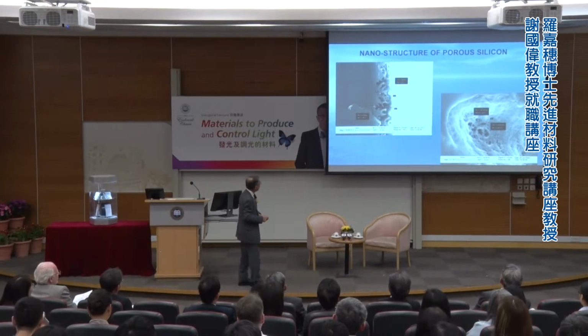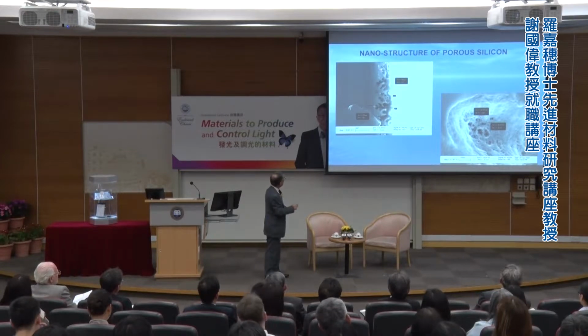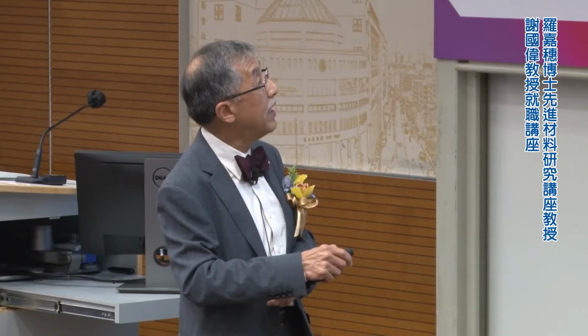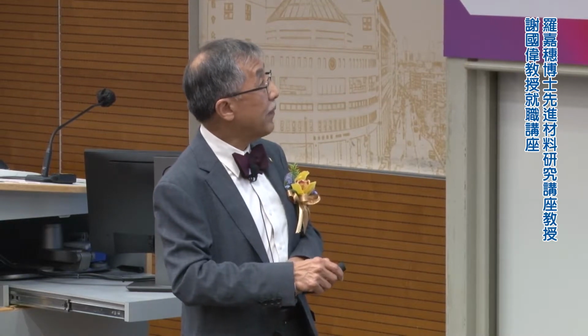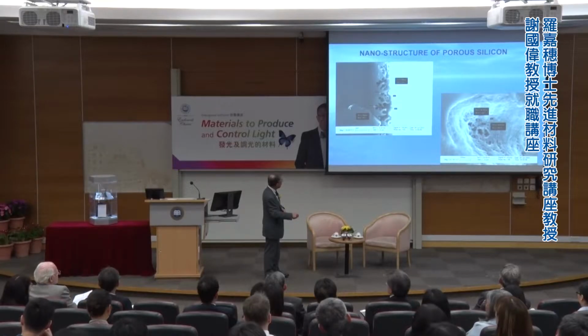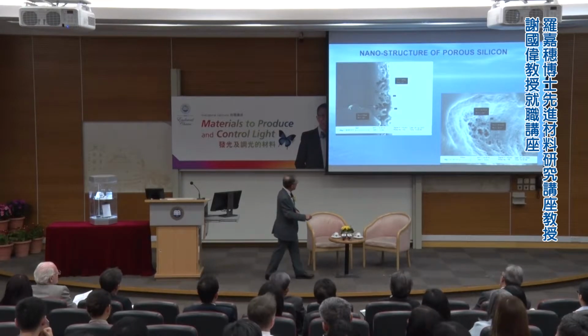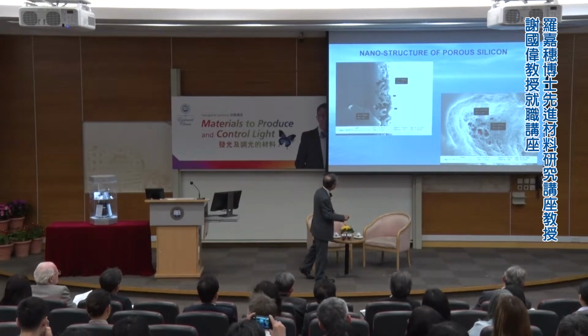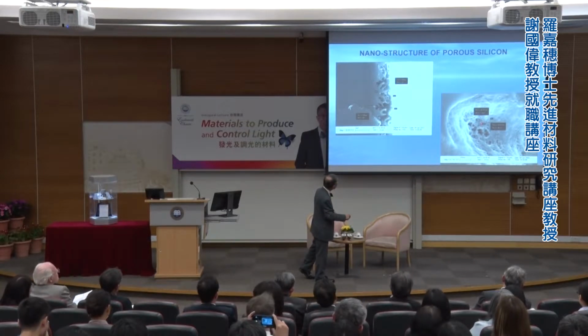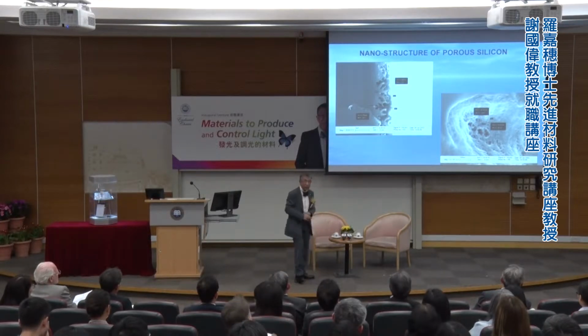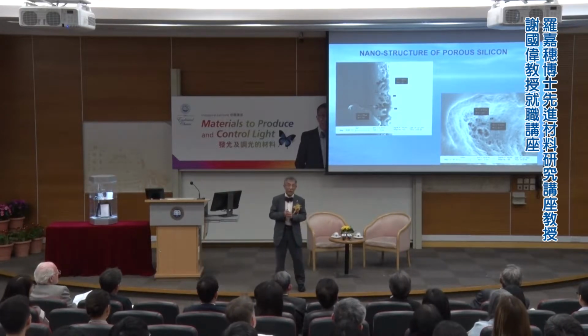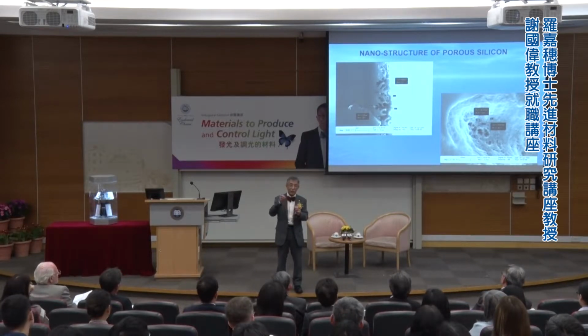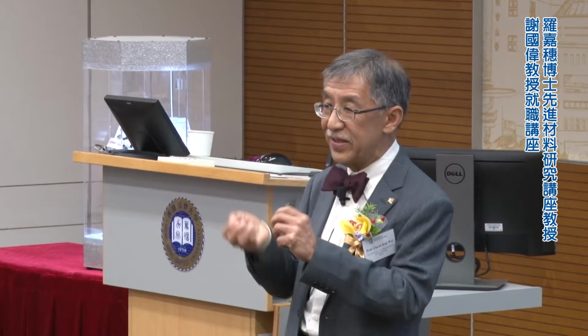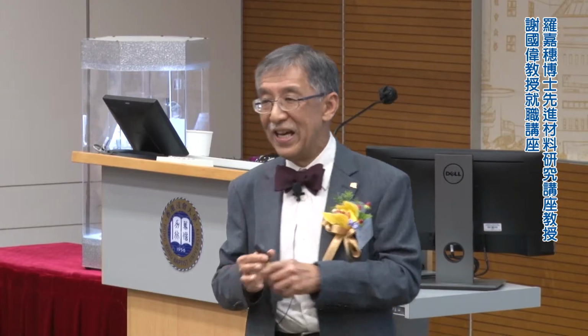So this is, in fact, you can see the cross-section of the porous silicon. This is a layer which is about a micron, and we etch into it, into lots of holes. These are the bigger ones, and within the bigger ones, you can see those very, very tiny ones. This part is about 10 nanometers, and those are about 50 nanometers. So they're very, very tiny holes. And what we did is that we put it in vacuum, extracted some gas. We could put other gases inside, different gases, and give you different colors. So that was quite fun, actually.